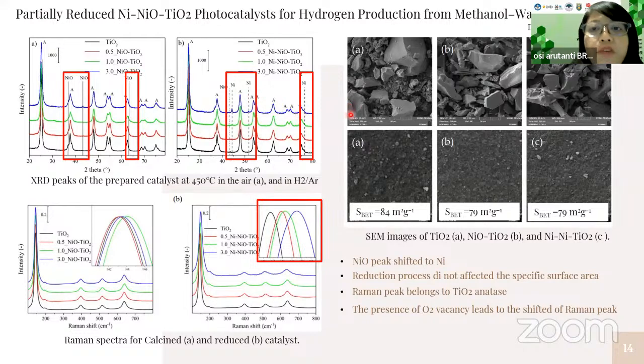How about the morphology? From the morphology, this is for pure titanium dioxide. This is for calcined titanium dioxide, and this is for reduced TiO2 with Ni. Here we can see from the same image that the addition of Ni didn't change the morphology significantly, only changed the surface area from 84 to 79, but the reduction process didn't affect the morphology and the surface area of the particle.